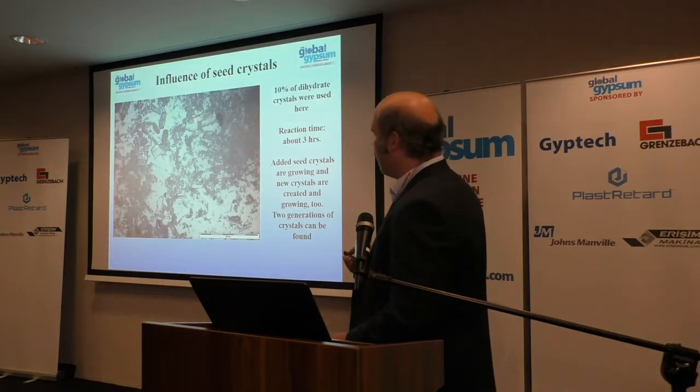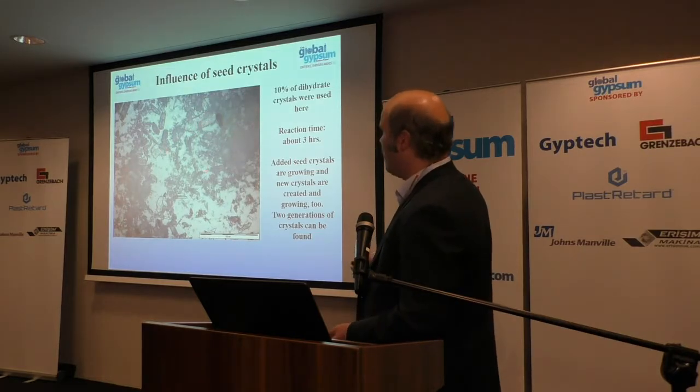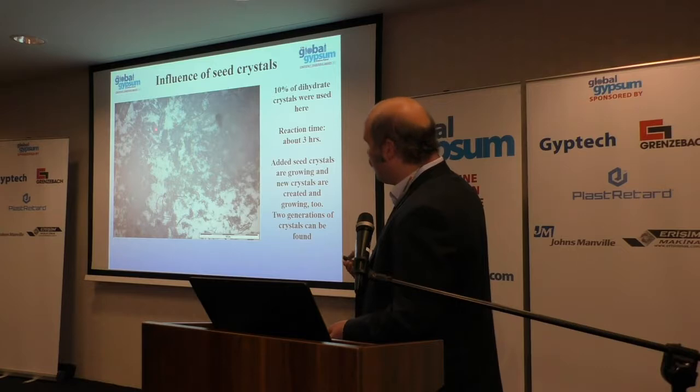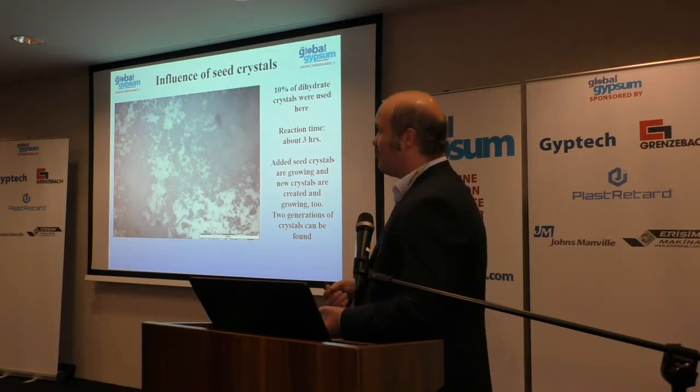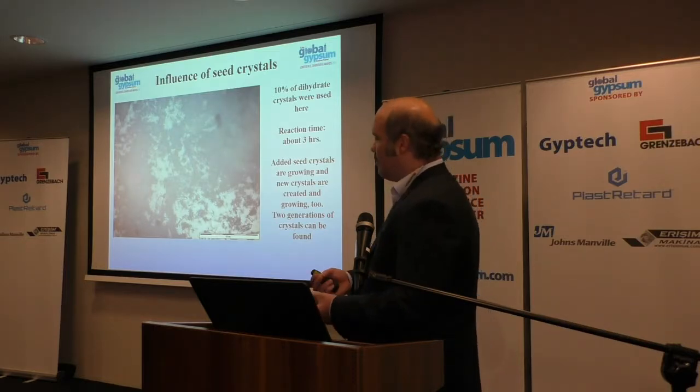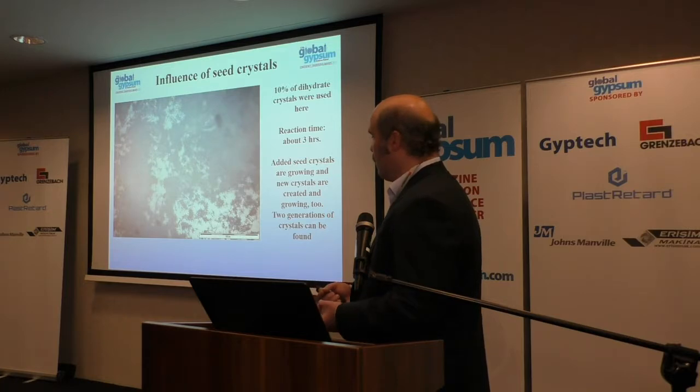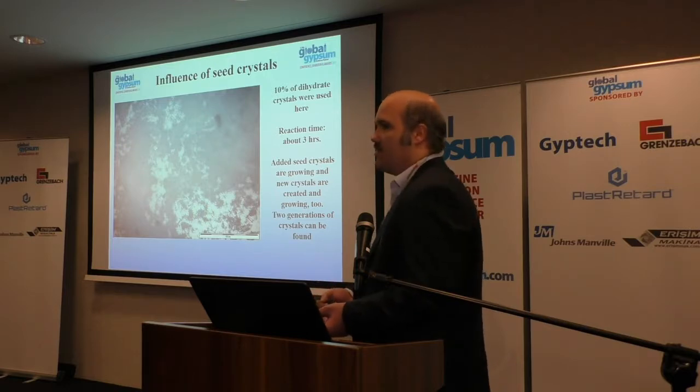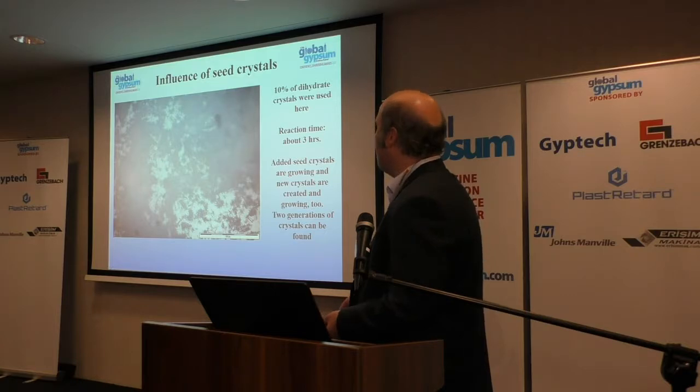We have these gypsum crystals here inside, they are still growing, and we have a seeding of small gypsum crystals out of a solution. So we end up with a mixture of larger and shorter crystals. And we could choose a little bit the particle size distributions of both, depending on the amount of dihydrate and the particle size of dihydrate we give in, and therefore we get maybe a better mixture, better technical properties of our materials just by changing the material we are using.